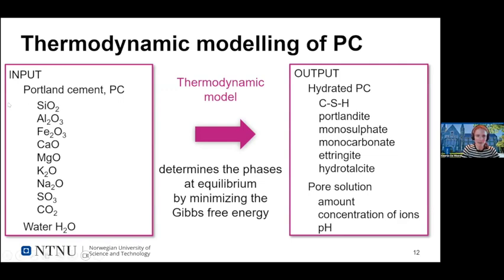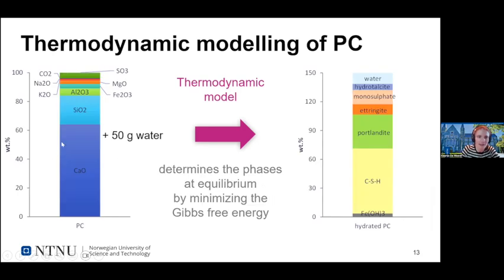So we need the composition of our Portland cement to calculate the hydrated assemblage and the pore solution. So here I try to visualize it. This is the composition of 100 grams of a typical Norwegian Portland cement. So you have the calcium oxide content, silicon oxide, aluminium oxide, and other oxides. And I add 50 grams of water to this 100 grams of cement. And then I let GEMS calculate which phase assemblage I would get at equilibrium.